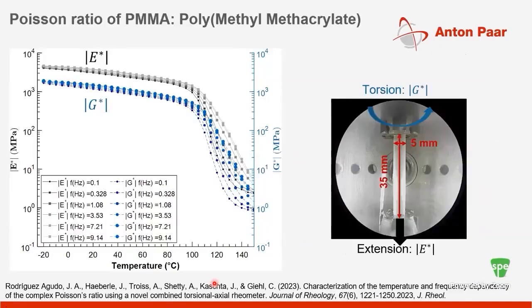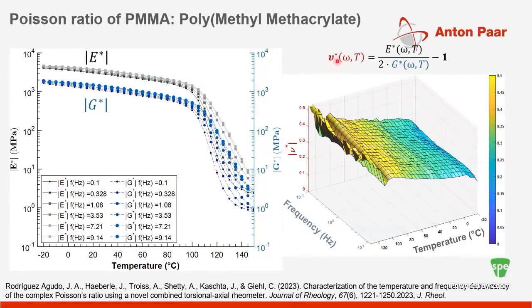There are review papers which discuss why cylindrical fixtures are preferred over rectangular fixtures, because you have warping and torsion type effects with rectangular ones. So we used cylindrical fixtures for this work, and this shows the complex dependence of Poisson ratio on frequency and temperature. For the most part, people assume Poisson ratio to be a constant, because the literature data on Poisson ratio is scarce to begin with.